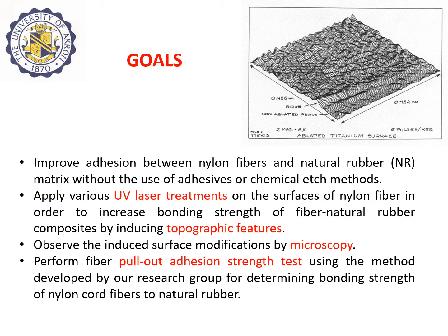We had the following goals for our study. We wanted to improve adhesion between nylon fibers and natural rubber without the use of adhesives or chemical etch methods. We wanted to apply various UV laser treatments on the surfaces of nylon fiber in order to increase bonding strength of fiber natural rubber composites by inducing topographic features.